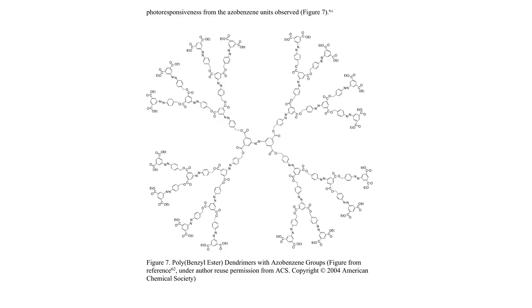The final example highlights a class of all-azobenzene dendrimers. Azobenzene is a molecule that can switch its shape from a trans to a cis form when exposed to light. By incorporating up to 29 of these units into a dendrimer structure across 4 generations, the authors created a highly photoresponsive macromolecule. This was achieved using a convergent method involving the condensation of protected nitroso compounds with 5-aminoisophthalic acids. These materials could then be studied as thin films, whose dielectric properties could be precisely controlled with light.